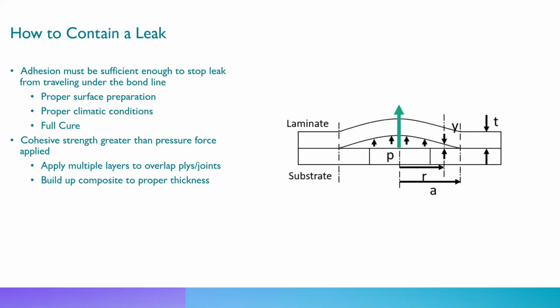That's a good thing with the ASME engineered wraps, that it's actually calculated. We have a lot of other systems that have extensive testing, so we know how thick it has to be to have that cohesive strength. And that's why we use composites, so that we increase the tensile strength and the cohesive strength of the composite to allow it to hold in the pressure coming from the leak. Same thing you would do with concrete and rebar. You're making it stronger so it can handle more loading.